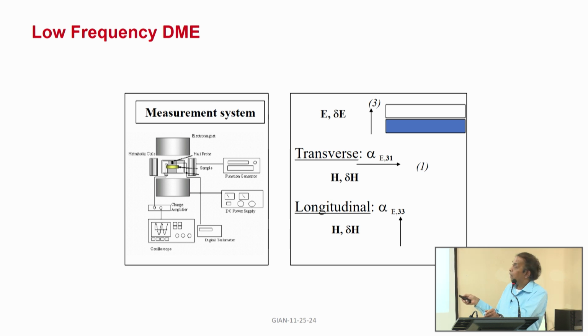And in the second case, all the fields are perpendicular to the bilayer. The poling is done in this direction. The AC and DC magnetic fields are also along direction 3, and then you measure the induced electric field or the voltage in this direction. That is all.